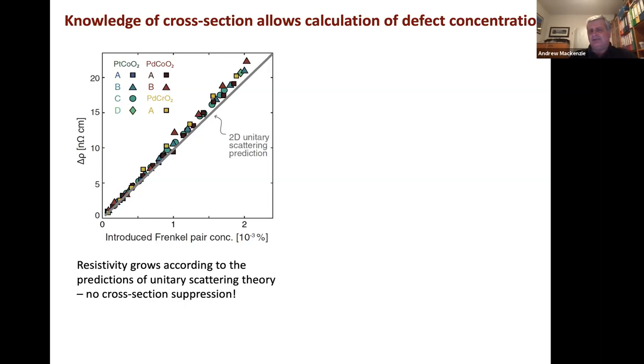You know, basically the idea here is we've put in a very modest number of defects. And as we've put those defects in a controlled way, the resistivity has risen just as fast as it does in anything else, right? Whereas if you were to try that with surface states in a topologically protected surface state, what you would see would be that you could make it more defected, but you wouldn't change your conductivity result, because the defects aren't controlling the conductivity. Here they are.